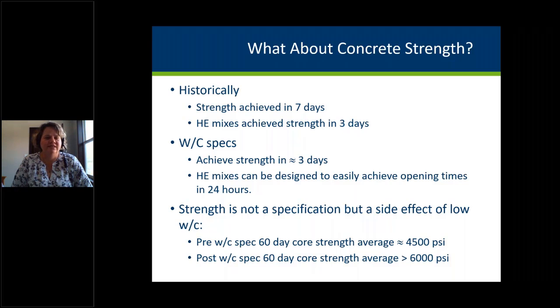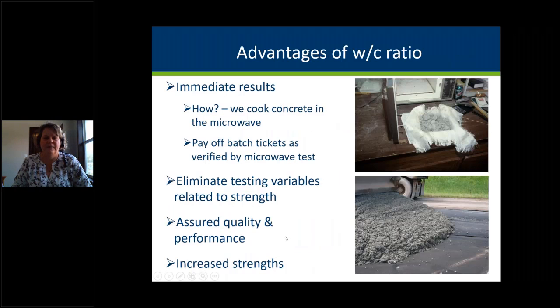It was typically achieved in 7 days. Our high early mixes, our design, were 3 days. Once we switched to water cement specs, they were starting to get that strength in 3 days instead of 7. And their high early mixes, they could get their strengths in 24 hours. When I say strengths, 3000 PSI compressive strength, or 500 PSI flexural strength is what I'm talking about. Strength is not a spec in our requirements, but it's a side effect of the low water cement ratio. And I have a little bit more data to show you on that.